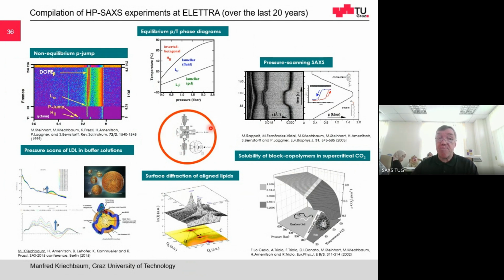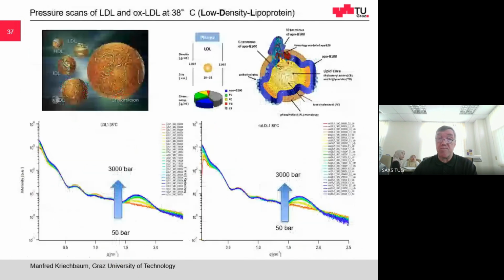We have done pressure jumps. We have mapped out phase diagrams, so phase diagrams as a function of temperature and pressure. We have done pressure scans, so we pressurize and depressurize, and we get different diffraction patterns. We have done it with supercritical CO2. So we have dissolved the detergent molecules or amphiphilic molecules in supercritical CO2 and seen the changes with high pressure. And we have also investigated LDL, low density lipoprotein particles under high pressure.